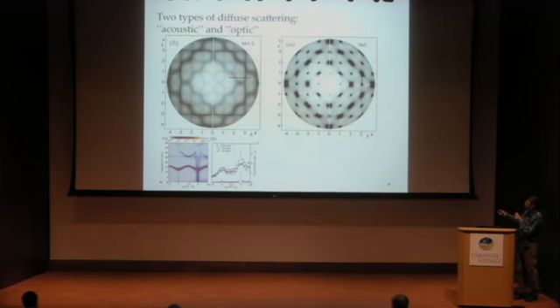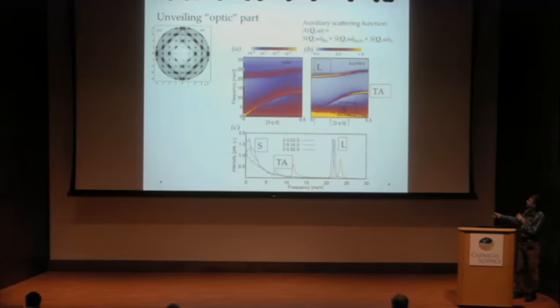I think I have time, so I will just go along the line, along the diffuse scattering line. That's where the intensity is strongest from that area. And then I get the usual dispersion, which involves the acoustic branch and the optic branch. This is the last mode, the higher frequency mode, the TO2 mode, if you wish. And the soft mode is here, it's the Slater mode, which is somehow, by some trick, making the higher contrast here. This is what you really measure, this is what we calculated.